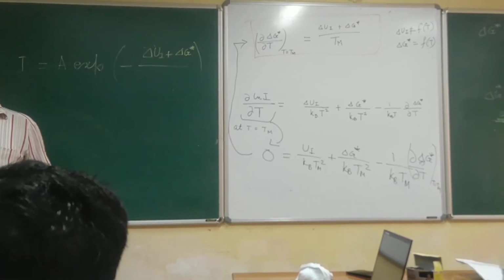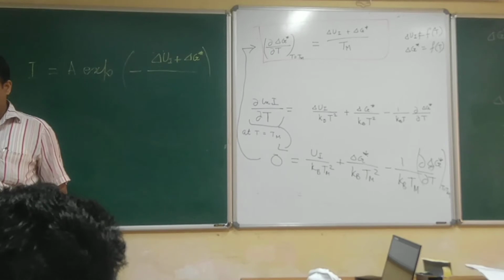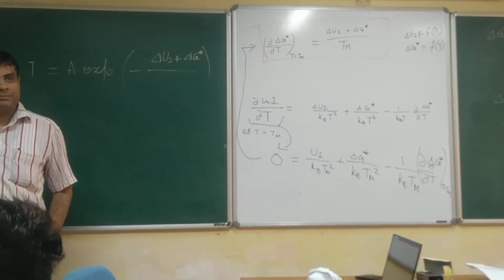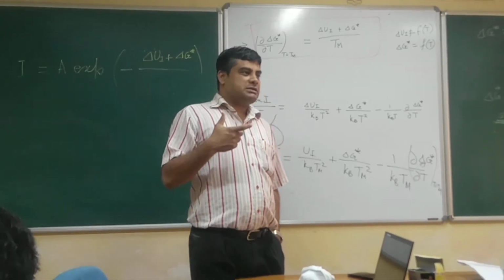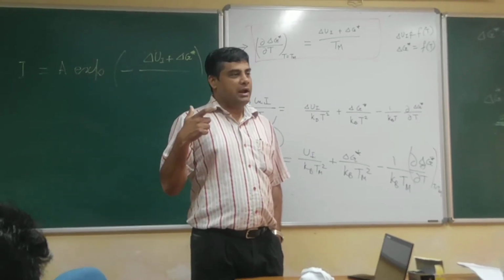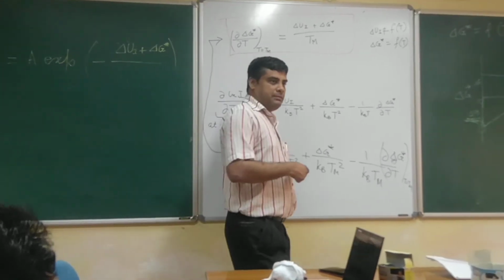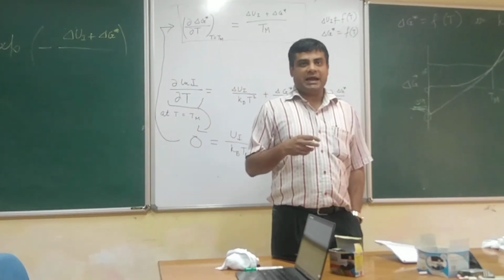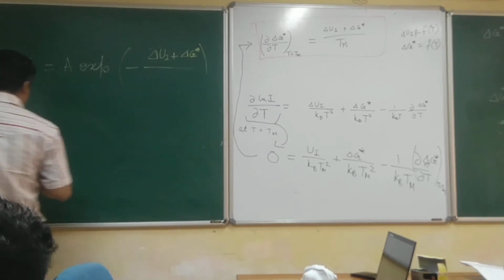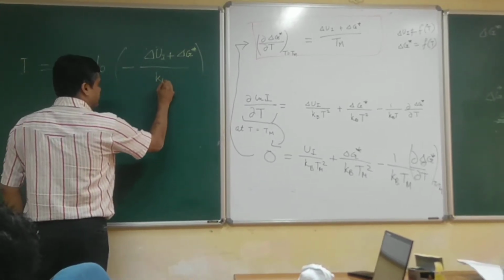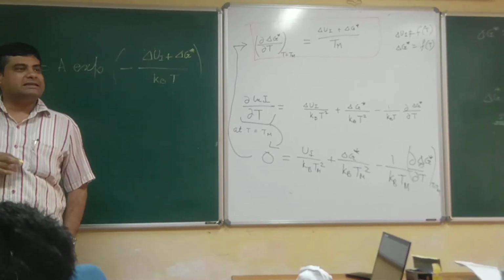That is, at high temperature it will be low, at a certain intermediate temperature it will be maximum, and at low temperature it will be low. So very close to the transformation temperature, because the transformation rate is low, the time required for a particular transformation will be huge. At very low temperature also the time required will be very high. At an intermediate temperature, the time required for a fraction transform will be less, and at a particular temperature it will be least. So we will get a C type of curve in the TTT diagram.